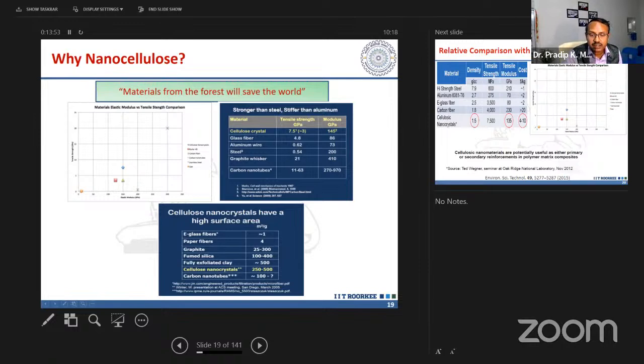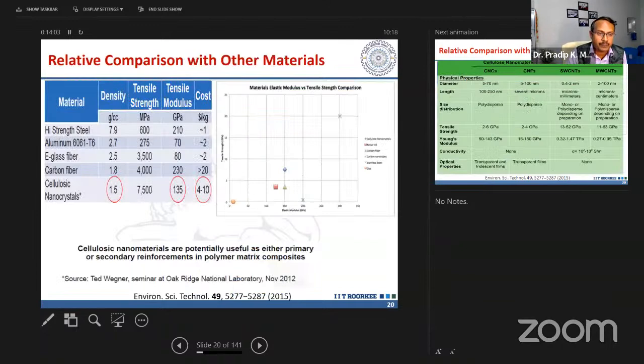If I compare with other materials like graphite, fumed silica, paper fiber, the surface area is very, very high, so we can utilize a minimum amount and it can help us. In relative comparison with other materials, if you see high strength glass or high strength steel, the tensile strength is 600 megapascals. Whatever we are getting with cellulose nanocrystal is huge, 7.5 GPa.